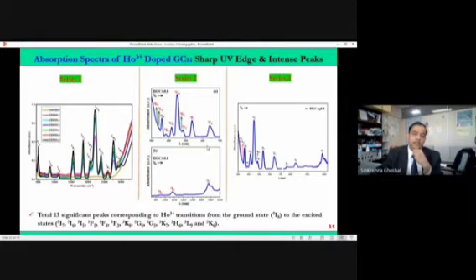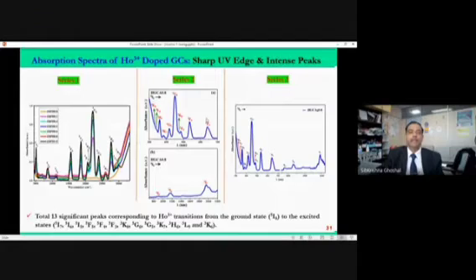Then we look at the structural symmetry. After looking at the structural dielectric correlation, then we go for the optical studies. Because remember, the main aim is to do the optical properties, but optical properties depend on the structural symmetry. So first we look at the absorption in all three series, and we see that as we are doping the nanoparticles in the system together with the rare earth, the absorption is becoming cleaner, and the absorption is really getting high. And some of the new absorption peaks, which were weaker without nanoparticle, become stronger with nanoparticle. So we are therefore on the right track.